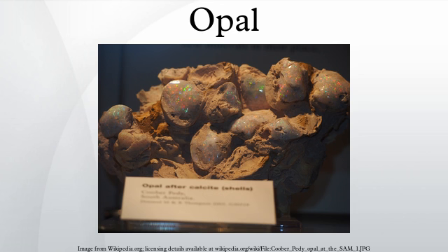Synthetic opal. As well as occurring naturally, opals of all varieties have been synthesized experimentally and commercially. The discovery of the ordered sphere structure of precious opal led to its synthesis by Pierre Gilson in 1974. The resulting material is distinguishable from natural opal by its regularity. Under magnification, the patches of color are seen to be arranged in a lizard skin, or chicken wire pattern. Furthermore, synthetic opals do not fluoresce under UV light. Synthetics are also generally lower in density and are often highly porous.